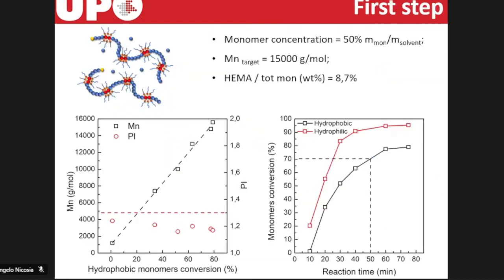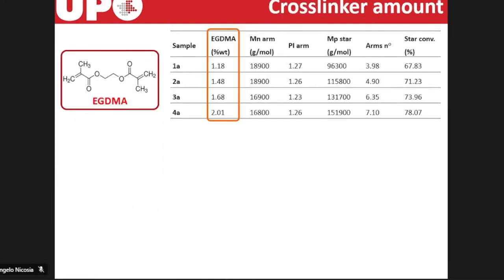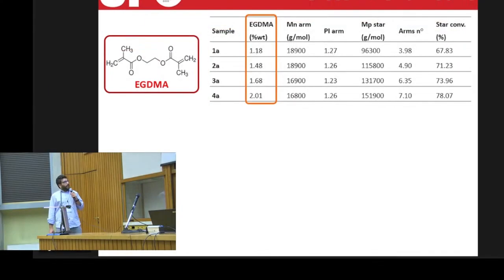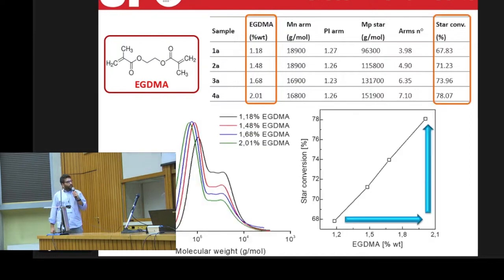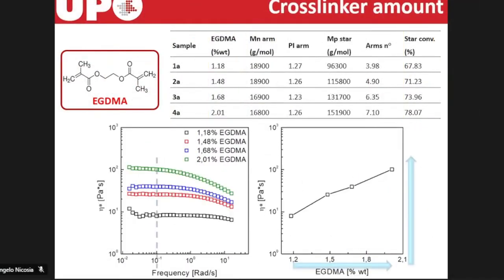We first optimized the synthesis of the polymeric arm, and as you can see, the molecular weight increased linearly with the expected parameters for this kind of reaction. Then we tried to optimize different parameters for the synthesis of star-shaped copolymers. Here I report the main cross-linker amount. In particular, we also see that by increasing it, we have an increase in the star conversion, and we observe the same behavior with the complex viscosity.